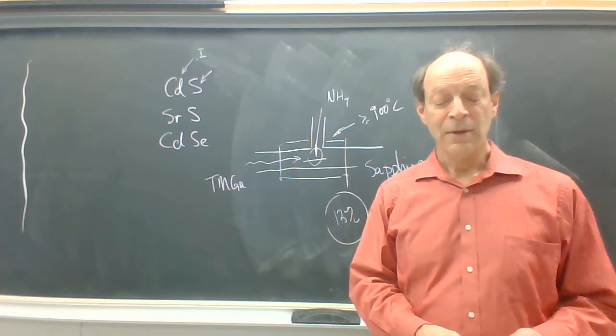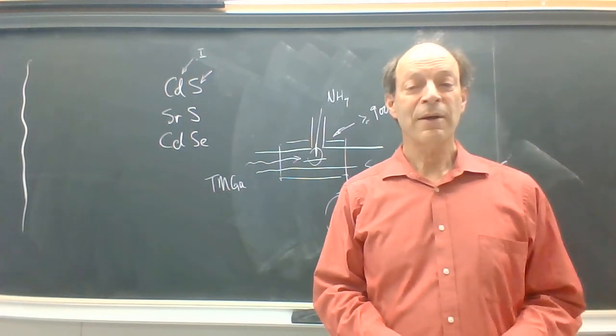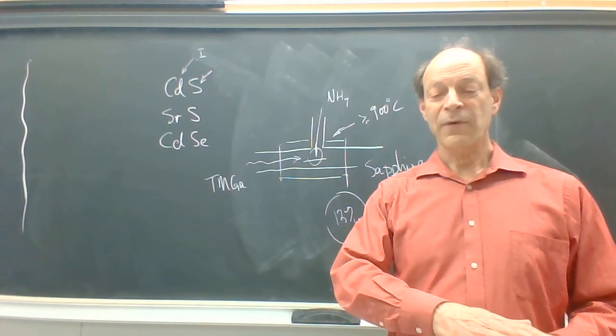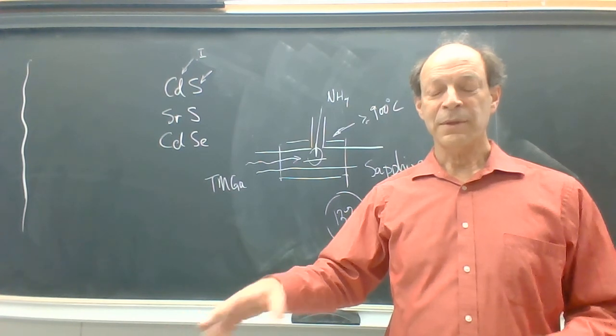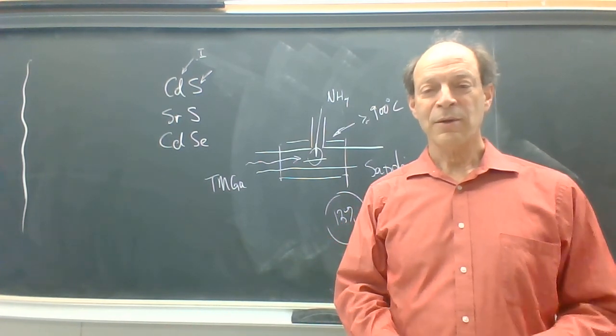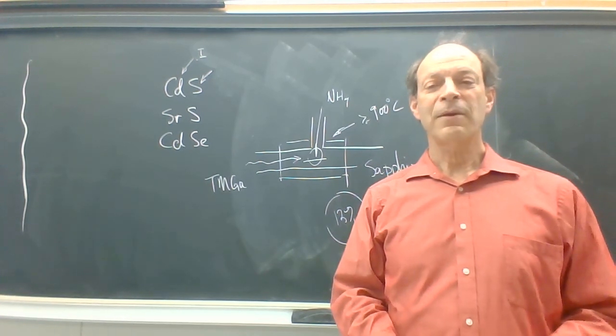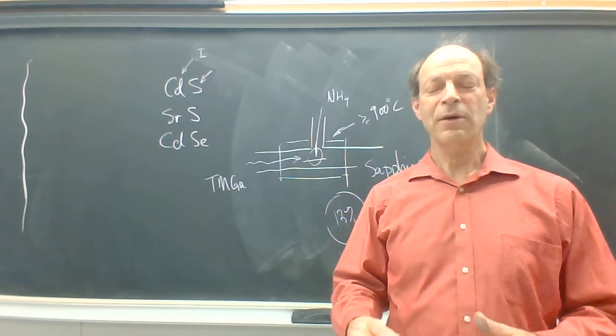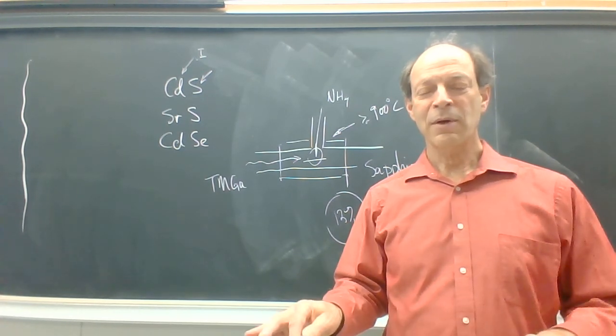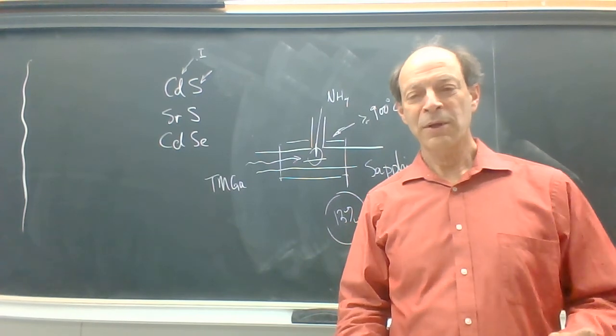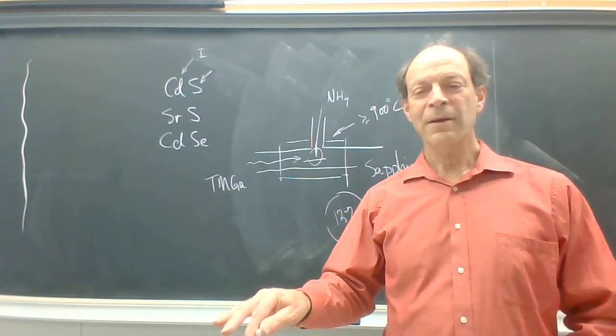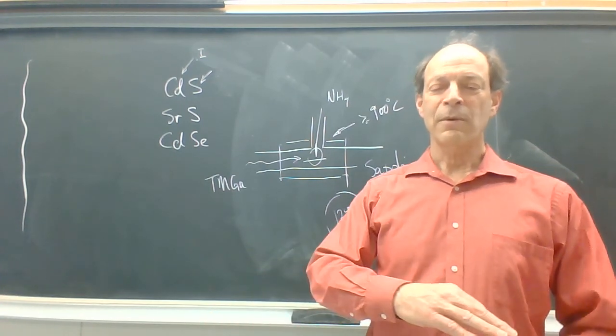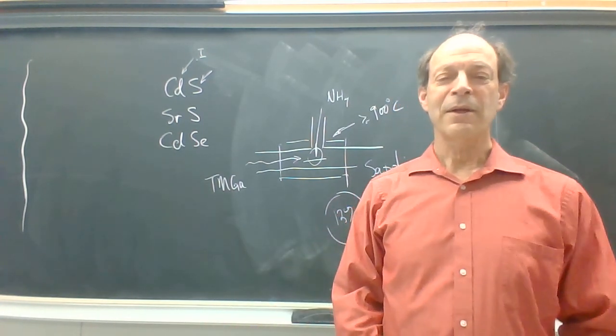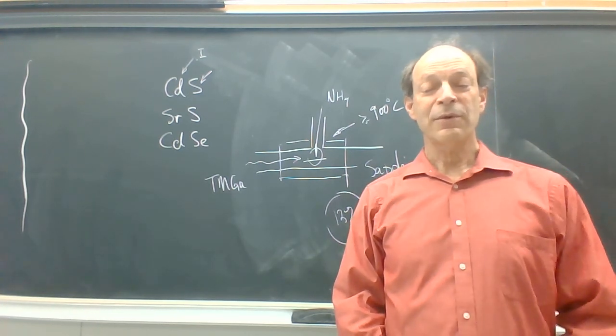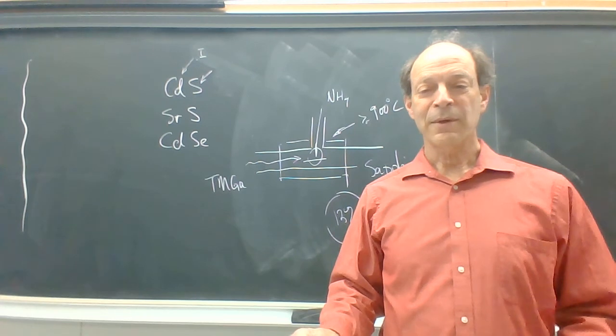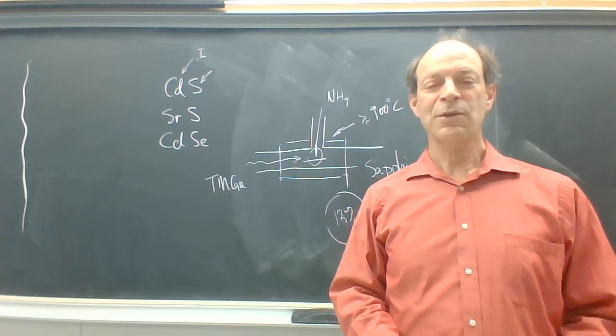other materials. So in the chapter on LEDs, you'll find a figure which plots, as a function of the number of defects in the gallium nitride, the quantum efficiency, and you'll find that the quantum efficiency, which means the radiative recombination rate in gallium nitride relative to the total recombination rate, stays rather high, well above, say, 50%, to a much higher defect level than in other 3-5 semiconductors. So that was, again, an unexpected result, but it enabled the use of this highly lattice mismatched substrate to be